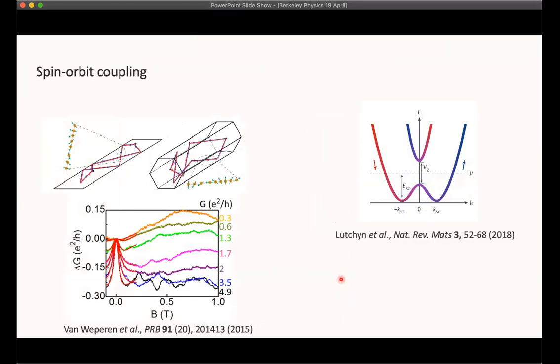So I'm going to briefly mention a couple of the experimental techniques we use to check those ingredients along the way, to make sure we've got the spin orbit coupling, the appropriate applied magnetic field, the induced superconductivity. So for example, how do we check that we have the expected spin orbit coupling? Because it's both a materials property and crucially, it is derived from the geometry of the system. So we can use a property known as weak anti-localization to probe spin orbit coupling.